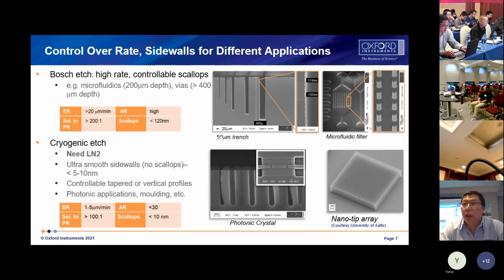Cryogenic etching needs liquid nitrogen to cool the lower electrode temperature to minus 100 degrees C. The high density plasma forms fluorine radicals to etch silicon. With low bias, the polymer is a silicon oxyfluoride. This is only a passivation at the lower temperature, minus 100 degrees C, and it keeps the bottom clear but protects the sidewall, which gives good selectivity to the photoresist and silicon dioxide masks. So the process can control tapered or vertical profiles.